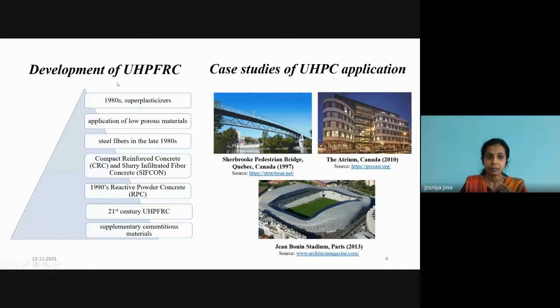So we can see a brief history of the development of UHP FRC. With the introduction of superplasticizers in the 1980s, the researchers were able to develop higher compressive strength, and with the inclusion of steel fibers in the late 1980s, the high strength matrix was aided with high ductility also. As a result, compact reinforced concrete and slurry infiltrated fiber concrete were produced. And in the 1990s, reactive powder concrete was also developed, and it has high compressive strength up to 800 megapascal, but the high production cost limited its widespread usage. And all of these led to the development of ultra-high performance fiber reinforced concrete in the 21st century.